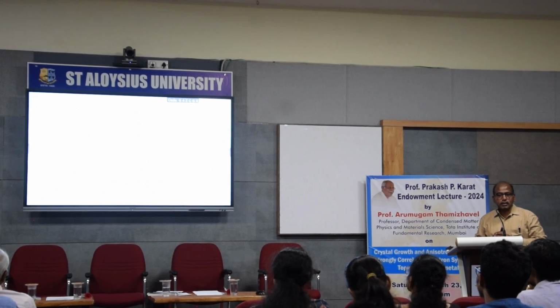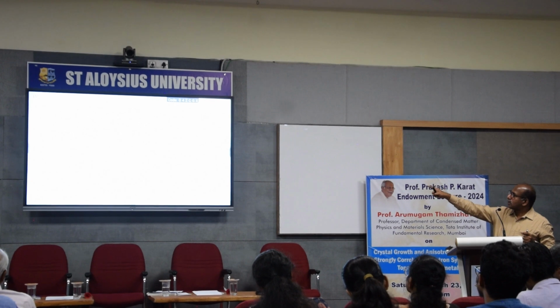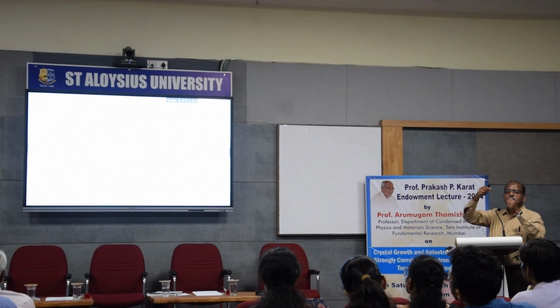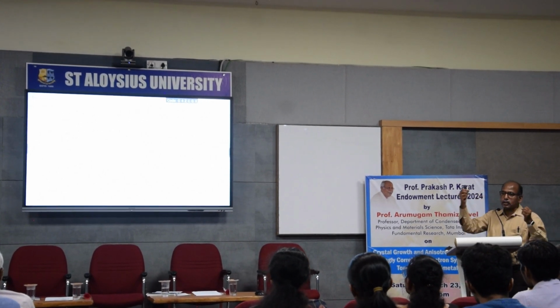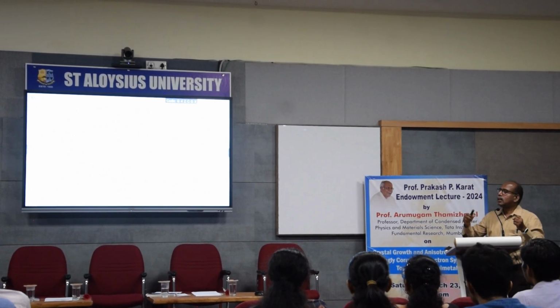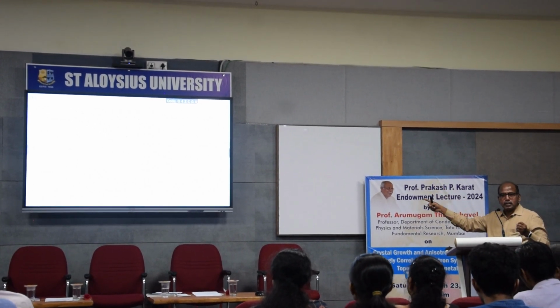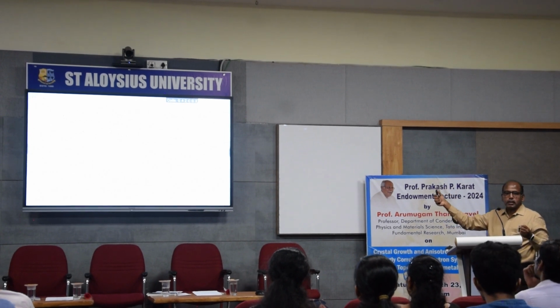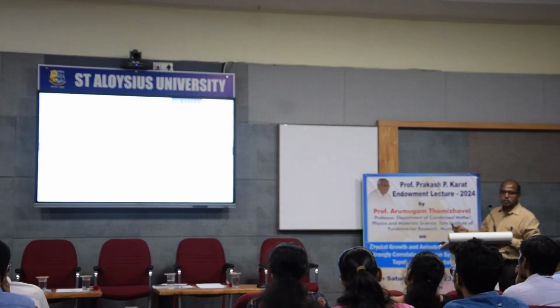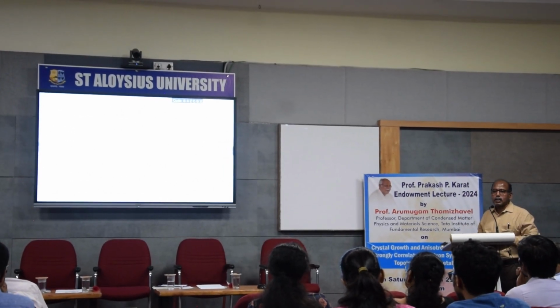That is because of the famous interaction called the RKKY interaction. The localized f electron, shown by this arrow, and these small arrows are conduction electrons. There is an exchange interaction happening between this local f electron and the conduction electrons. Depending on the strength of this exchange interaction, the conduction electron passes the information to the other f electron at a far off place, telling it, okay, you align in the upward direction, you align in the downward direction. That is how magnetism arises in rare earth based intermetallic systems. This is very popularly called the RKKY interaction.